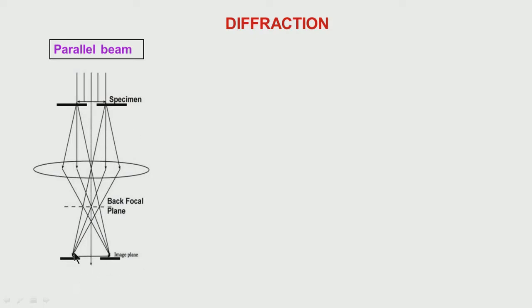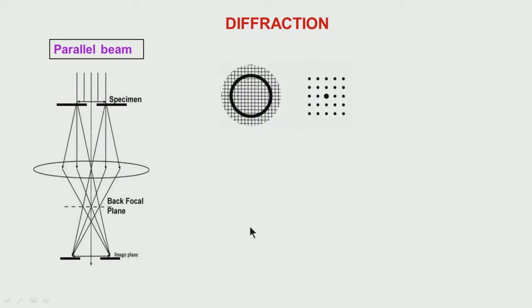If you put an aperture in the image plane, that is equivalent to putting a virtual aperture on the object plane, which is demagnified. That way, using a larger aperture, we can effectively choose any area on the sample. This sort of diffraction, we call a selected area diffraction. In selected area diffraction, we put an aperture in the image plane that decides from which area of the sample, though the beam is falling on the large area, the diffraction is being taken.